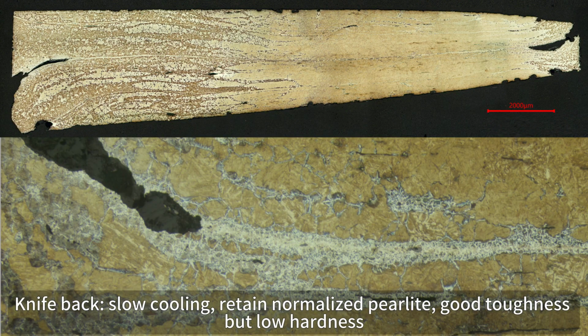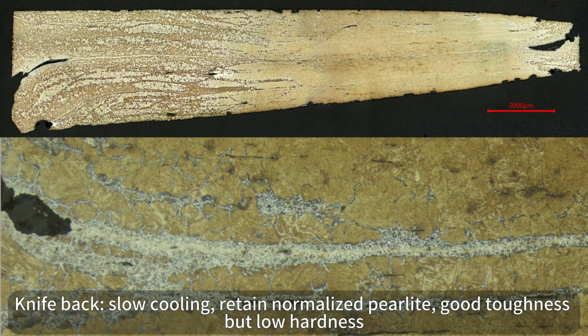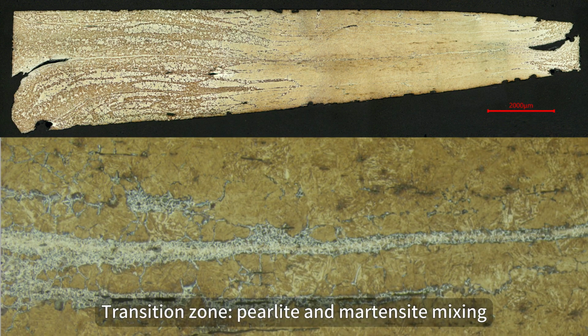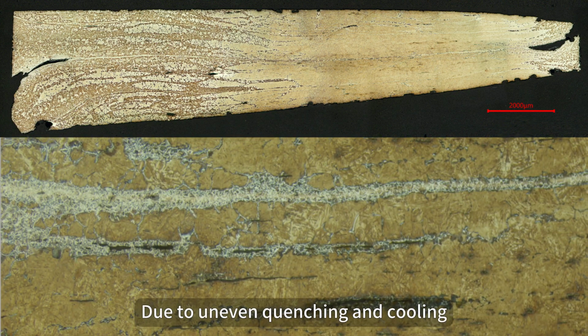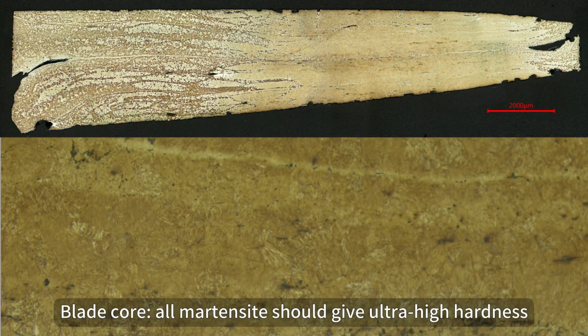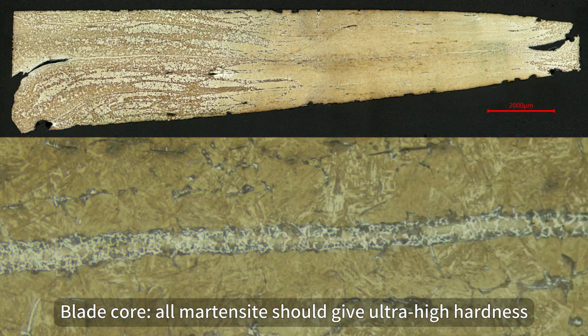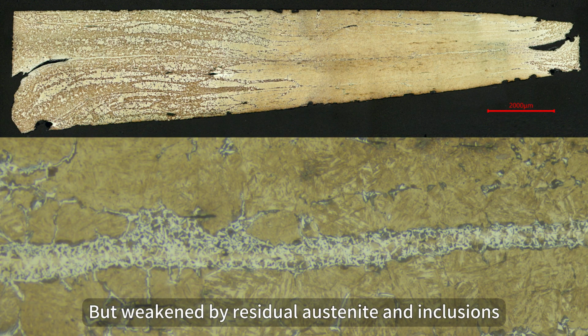Knife back. Slow cooling. Retains normalized pearlite. Good toughness but low hardness. Transition zone, pearlite and martensite mixing, due to uneven quenching and cooling. Blade core. All martensite should give ultra-high hardness, but it is weakened by residual austenite and inclusions.